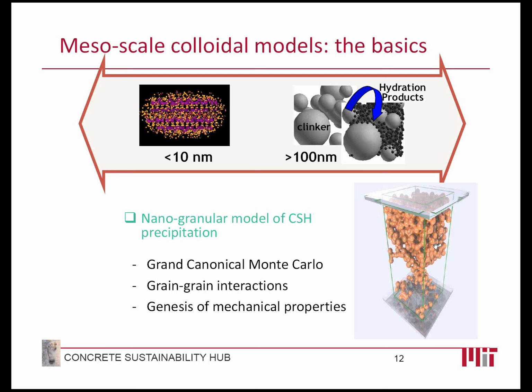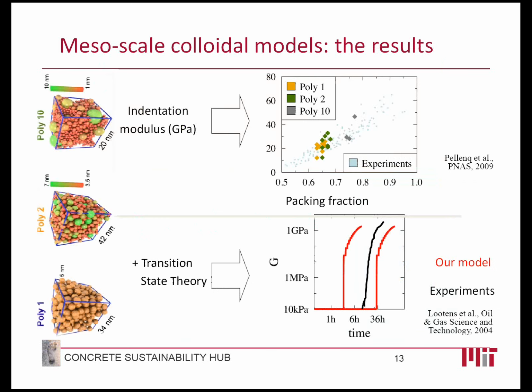So this is the model. Basically, from atoms upscale, we first design grains at the scale of nanometers. We have good experimental reasons to know that the grains are on the scale of a few nanometers. What we do is simulate the precipitation of those CSH grains, on the left, in between the clinker phases. That's the little cartoon on the right, and you see those black dots that are CSH grains in between clinker phases. We do this nano-granular model of CSH precipitation, which relies again on statistical physics, called grand canonical Monte Carlo, based on knowing the grain-grain interaction, so the CSH grain interaction between two of them, or the clinker CSH interaction, for instance. That gives us a way to predict the mechanical properties as setting occurs.